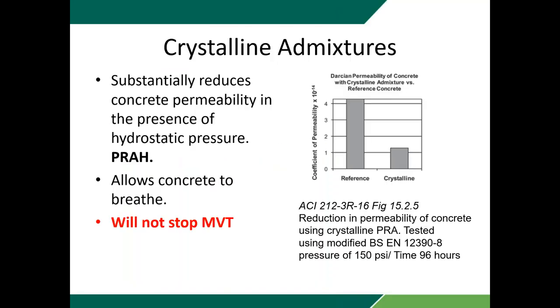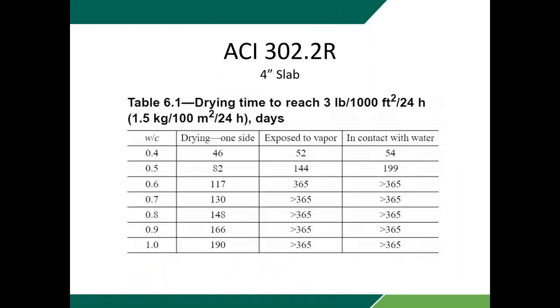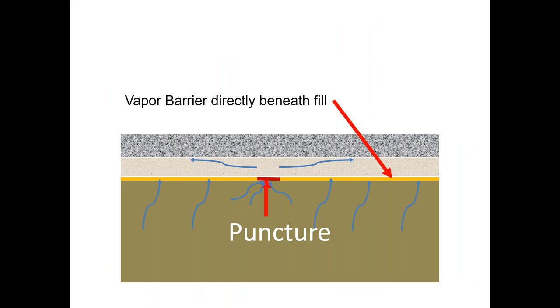So if I've got that sand layer below the slab, and the water from the concrete, let's say, goes into this sand layer immediately after you poured the concrete, I think what he's implying is that the concrete can dry because the moisture is moving down into the sand. If I've got a vapor barrier below that sand, there's nowhere for that moisture to go. You still got moisture there and it has to leave. And the only way it can leave is up through the concrete. It can't evaporate. Even if it moves laterally, there's no place for it to move.